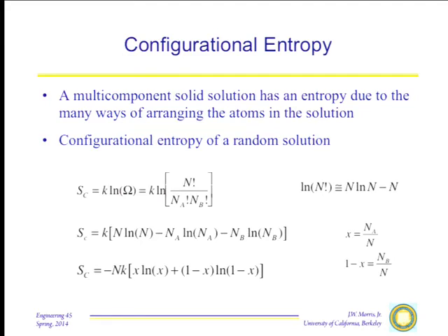Well, in fact, if you make a solid solution, at reasonable concentration you won't really have a random distribution of atoms. The reason is that the A atoms will either like other A atoms or they'll prefer B atoms, so there will be a tendency for the atoms to cluster, and the entropy will not be precisely equal to the value you get from a random solid solution. But it's not that far off in general.